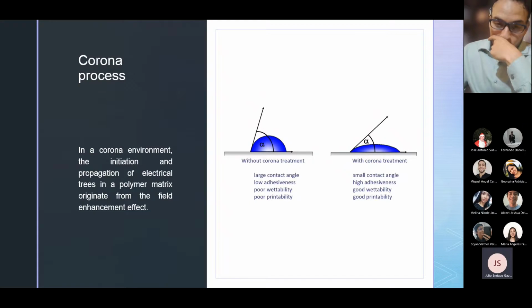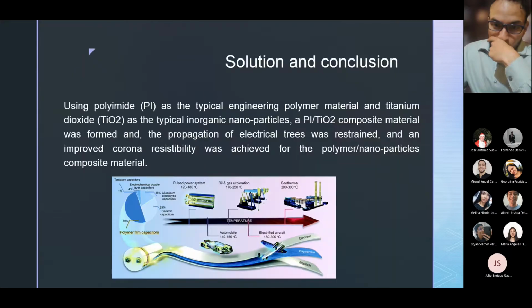And what is the corona process? The corona process in polymeric materials has the objective of improving the wettability of the surface by increasing the energy and introducing polar groups into the surface. And what is the solution? The solution is a composite material, the polymer and nanoparticles, specifically polyimide and titanium dioxide.